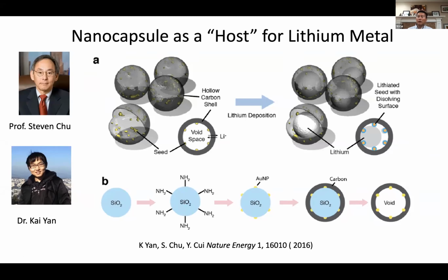One thing to also mention, this carbon is, of course, all types of carbon. If you put in a lot of polar functional groups, oxygen, nitrogen, and they start to like lithium, then lithium nucleation might happen also on carbon as well. Let me go down and then I will show you the so-called wettability with lithium metal. The affinity with lithium metal, depending on what type of carbon you use, is important.